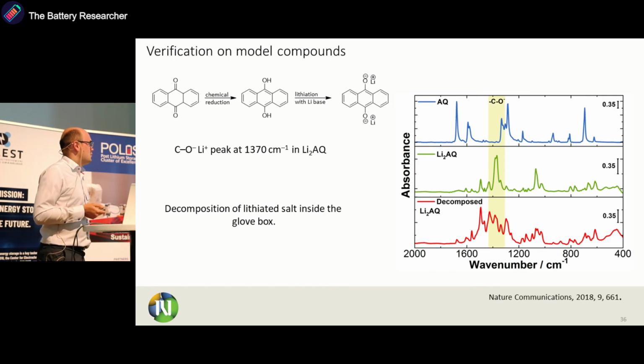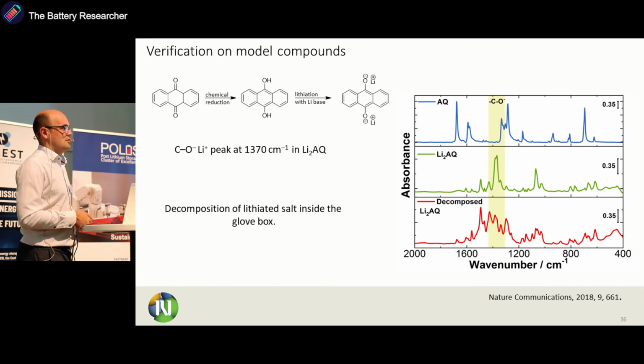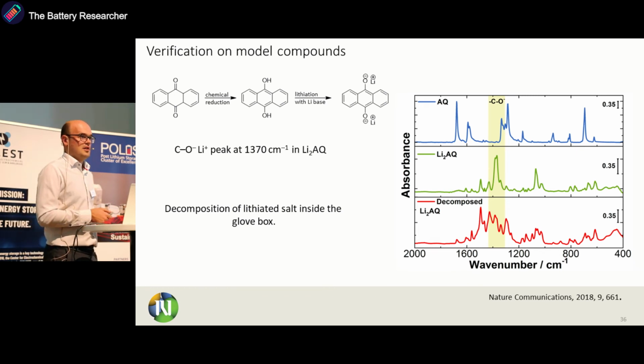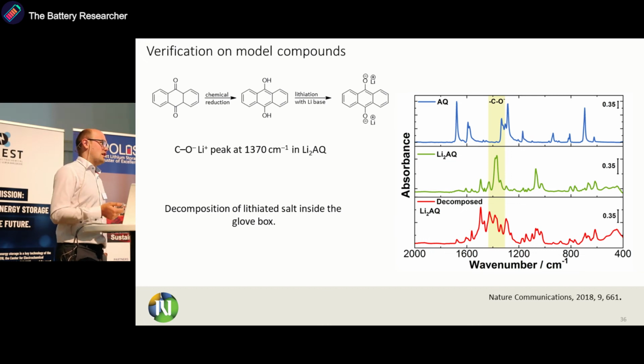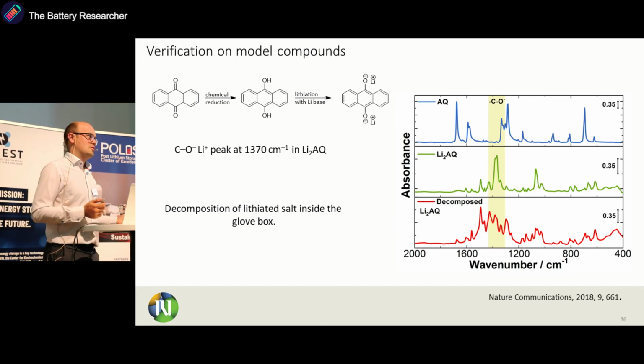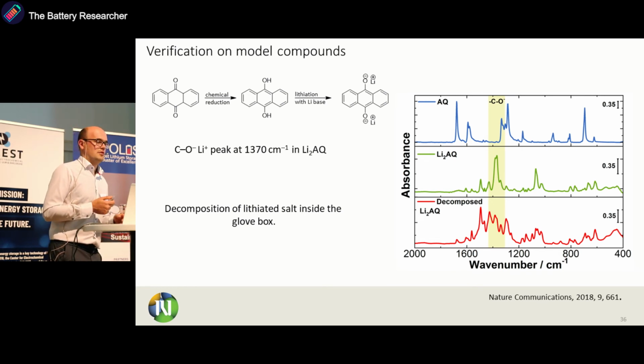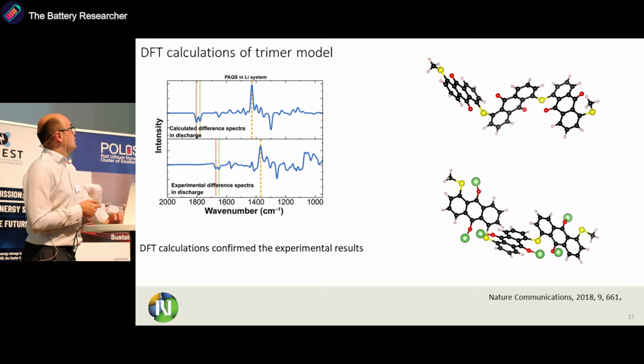But one problematic thing that we saw is that even when we stored this in the glove box for 2 weeks, it decomposed. This means that with ex situ samples, you have to be really careful to measure them in the glove box, not expose them, and measure them quickly, because in a matter of a few days or weeks, they can be completely different. We also did DFT calculations on a trimer. To confirm this, we used a trimer because this was the maximum size that we could use for DFT calculations. And if we compare the difference spectra of calculations and experiment, we can see that we have really good agreement.